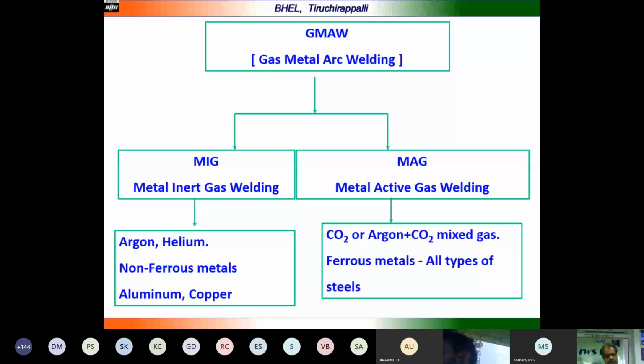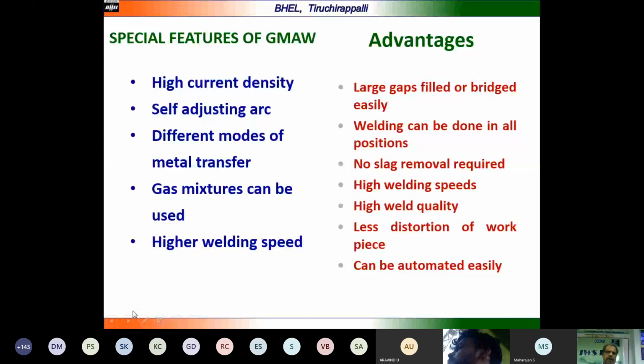The special features of the GMAW process are high current density, and the arc is a self-adjusting arc. Because of the current feed, the arc length can be maintained. It is a property of the process. If the wire feed is more, then the current will slightly increase, and then it will maintain the arc length. Or if the wire feed is less, then the burning rate will be slowed down a little bit, and then the arc length can be maintained easily in the semi-automatic welding process.